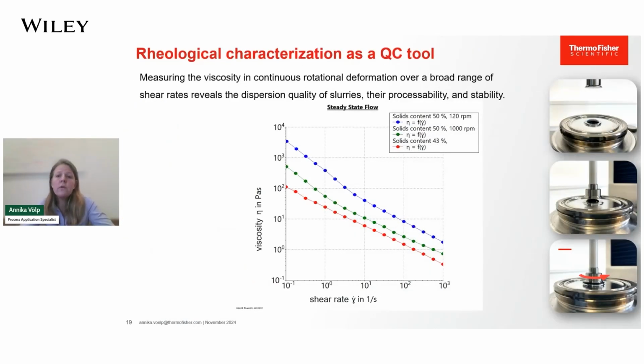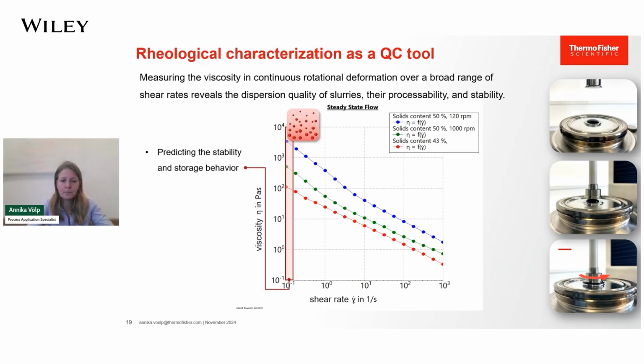Electrode slurries usually show a so-called shear thinning behavior, which means the viscosity is decreasing from high values at low shear rates to low values when the shear rates are increasing. For many complex fluids, including electrode slurries, this is a desired behavior because high viscosities at low shear rates, or at rest, show sedimentation or slow down the sedimentation or aggregation effect significantly, leading to a better shelf life and less need for agitation during storage. High shear rates, on the other hand, occur when the material is applied to the current collector foil via the slot die coating.